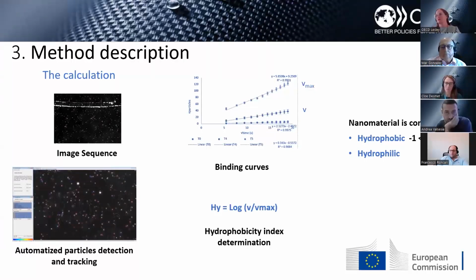Once you have this data, you are able to calculate the binding curves of the material on the 3 different collectors, and then determine the hydrophobicity index, defined as the logarithm of the ratio between the binding rate of our nanomaterial on the hydrophobic collector with minimum attachment and the binding rate on the collector with maximum attachment.